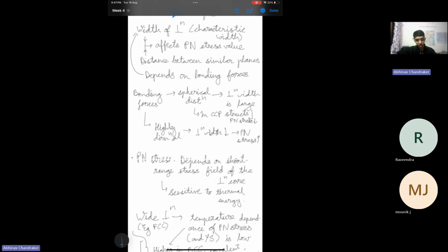So the width of a dislocation, or a characteristic width, is basically an indication of how much is the distortion, to what length scale is the distortion which has occurred in the alloy. If the width is high, that means the distortion is over a larger area, and that in a way signifies that the distortion is not concentrated, so it will be easier for the dislocation to move. But if the distortion is concentrated, that is the width is very low, then the movement will require a very high activation energy, because the process involving bond switching will be difficult in that scenario. Sir has shown it visually very well in his lecture.